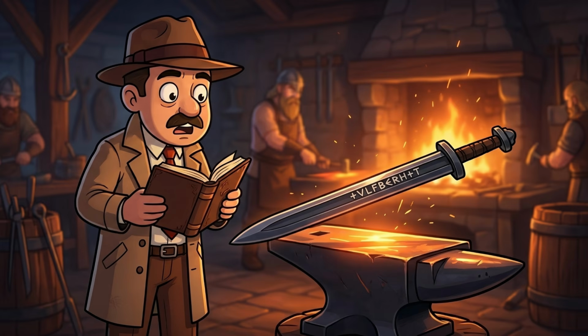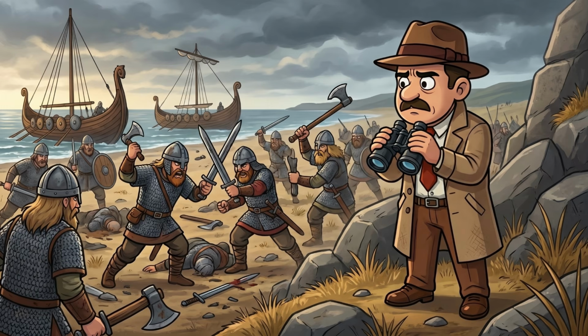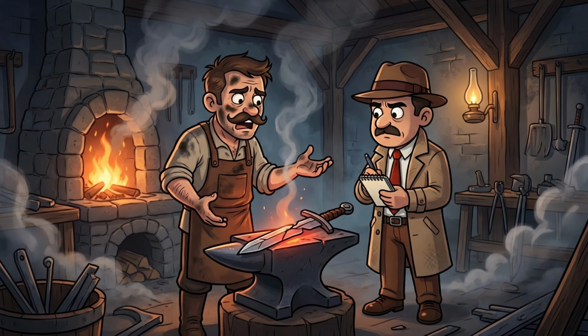Their steel was too clean, too advanced, and too far ahead of the world that supposedly made them. The Ulfberht swords date roughly from the 9th to the 11th centuries, a period often imagined through raids, wooden ships, chainmail, and brutal close combat. Most European blades of that age were made from bloomery iron filled with slag and impurities. They could be effective, but inconsistent. Many bent, some cracked. Their quality depended heavily on the skill of the smith and the limitations of the furnace.